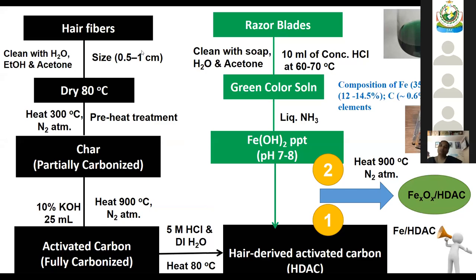On the left hand side, you clean the hair with water, ethanol and acetone, and cut the hair fibers into size 0.5 to 1 centimeter level, and dry in 80 degree dry air oven, and heat at 300 degree in nitrogen atmosphere. It's a preheat treatment. The hair fibers are completely charred or partially carbonized. This carbonized material is mixed with 10% potassium hydroxide, 25 ml, and heated at 900 degrees in nitrogen atmosphere, we get the fully activated carbon, fully carbonized. So this carbon contains high porosity and also highly graphitic carbon layers.